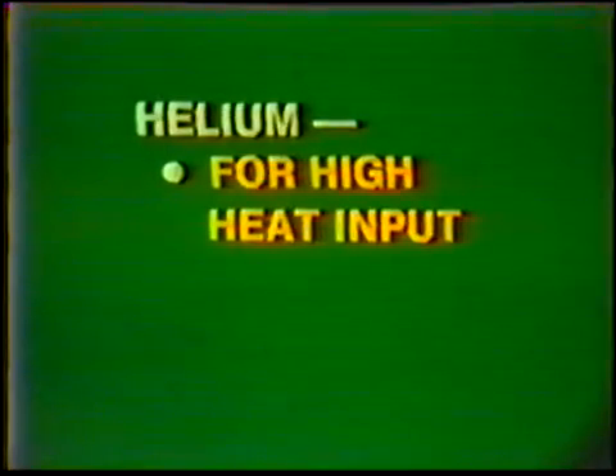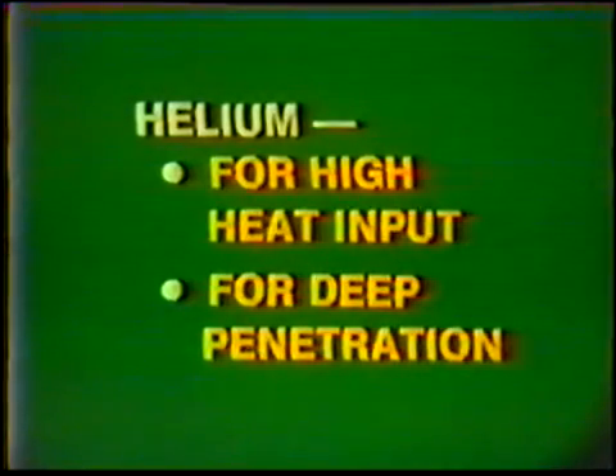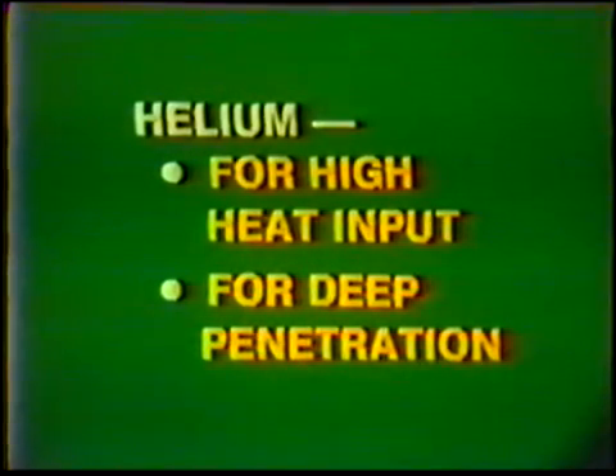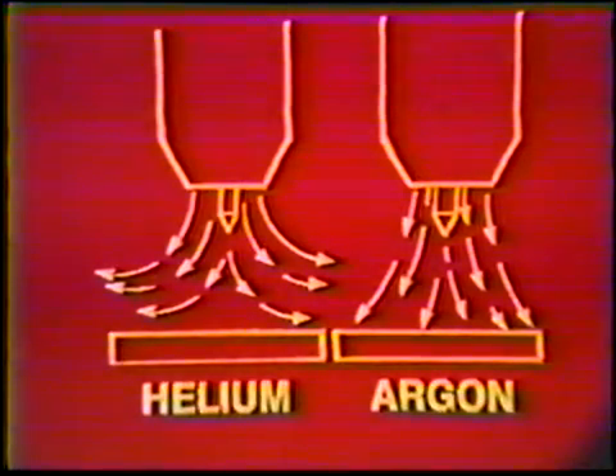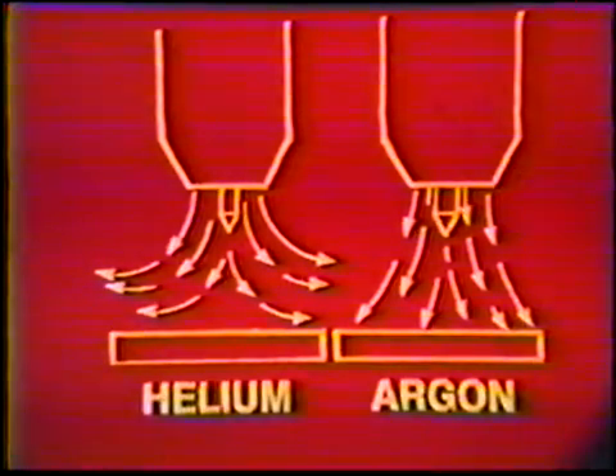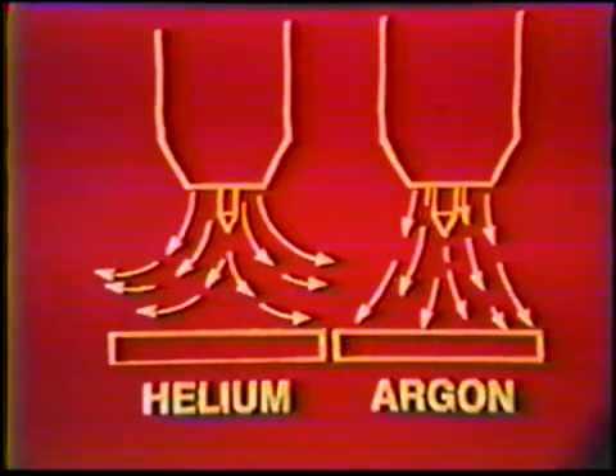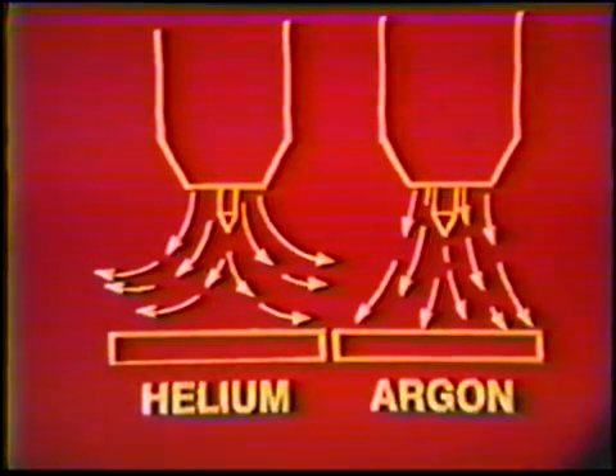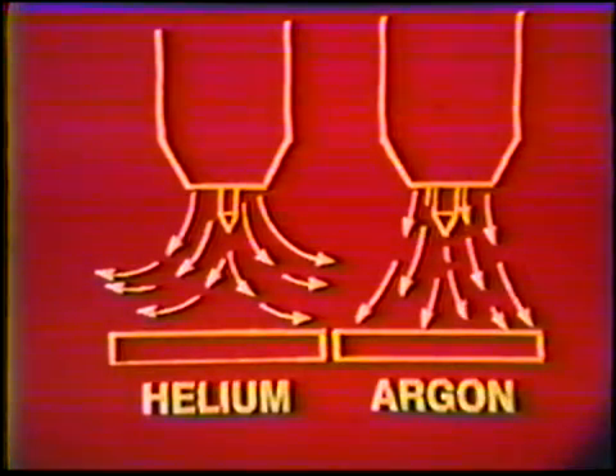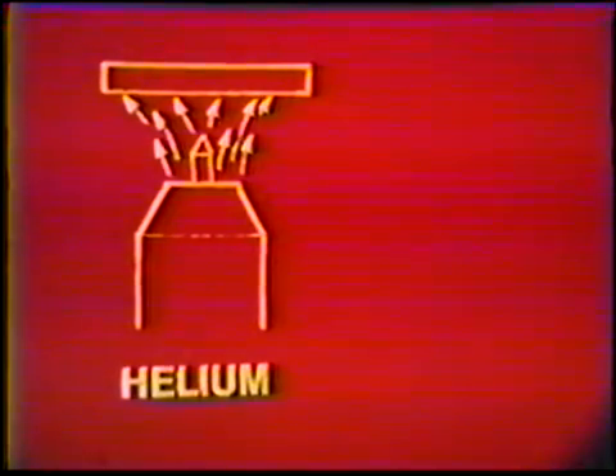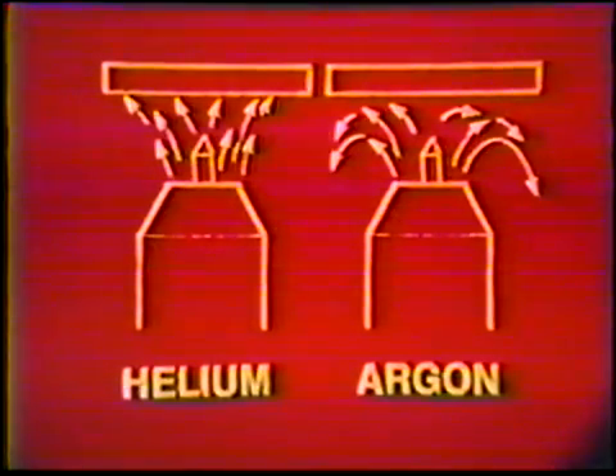Helium is normally used on heavy aluminum weldments where high heat input is required to produce deep root bead penetration. This is due to the greater arc voltage associated with helium as compared to argon. Argon is heavier than air, causing it to remain in the arc area when the puddle is below the nozzle. This makes it necessary to double the gas flow rate for helium in these positions. Helium is lighter than air, which is ideal for positions such as overhead, which locate the puddle above the gas nozzle.